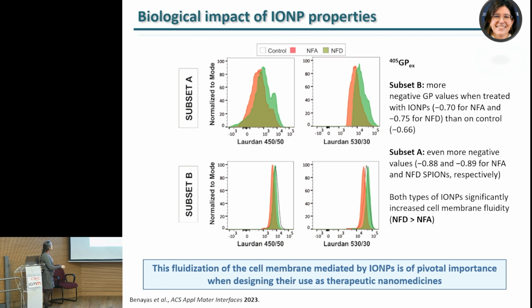Let me remind you that we think it has a higher dose of incorporated nanoparticles. The subset was mixed. If we look at the subset B first, that is the closer to the normal, the values got more negative. So already a significant difference. But if we go to the subset A that has a higher amount of nanoparticles incorporated or interacting with the cell membrane, it gets even more negative. So there is a clear impact of the iron oxide nanoparticles on the fluidity of the cell membrane.